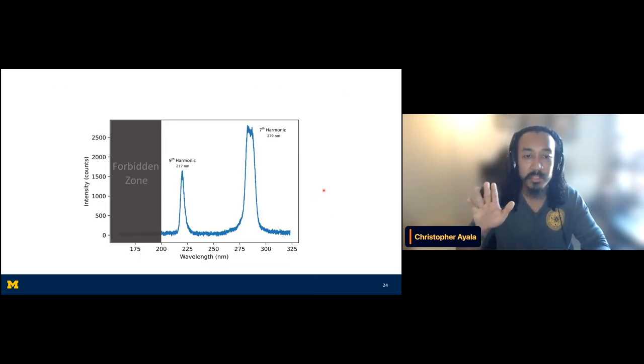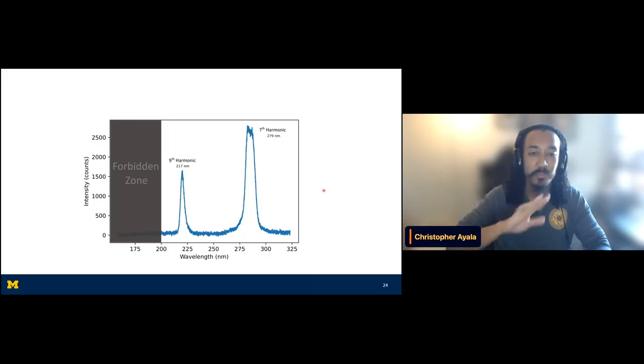If we take that same two-color system and turn it into a one-color system and send it into a high fidelity spectrometer, we're able to actually even see the ninth order harmonic sitting here at around 217 nanometers. What I have labeled here on the side as the forbidden zone just refers to vacuum ultraviolet. Vacuum ultraviolet refers to the point at which air starts absorbing light. So if you do not have a vacuum spectrometer or something, or all of your material is in vacuum, anything that's produced under 200 nanometers, pretty much you wouldn't be able to see.